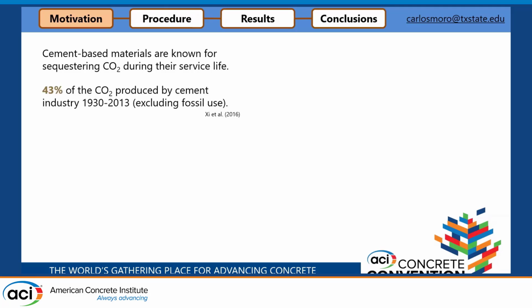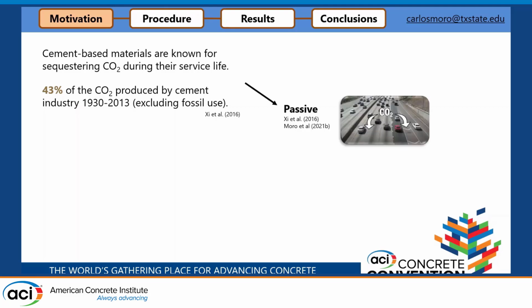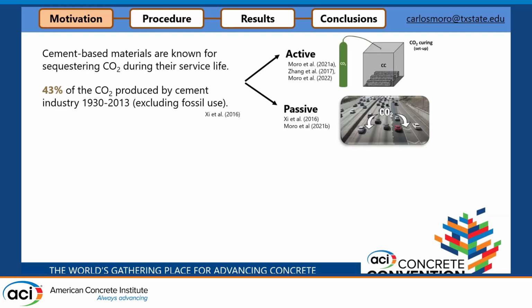And indeed, some research quantified that 43% of the CO2 produced in this period of time, so in these 70, 80 years, was taken up by the cement elements, the concrete elements. We know that there are two ways of uptaking CO2. One is passive, natural carbonation, the typical carbonation that we all hear about, and then the active one. The active one is using CO2 curing, using carbon cure technologies like liquid CO2 inside the mixer.